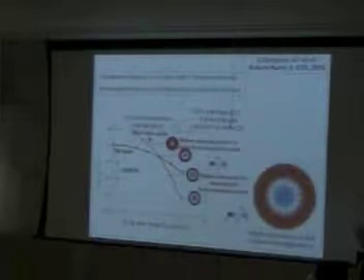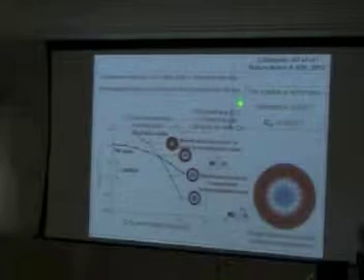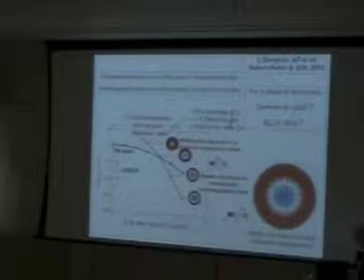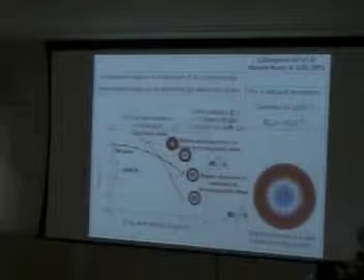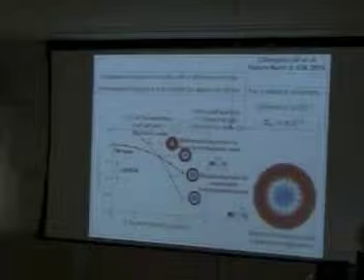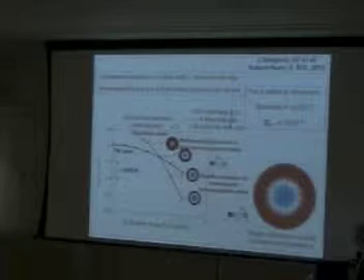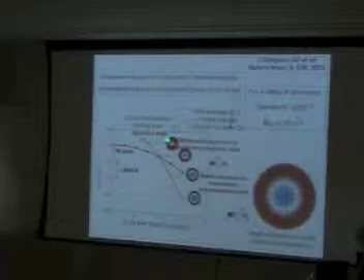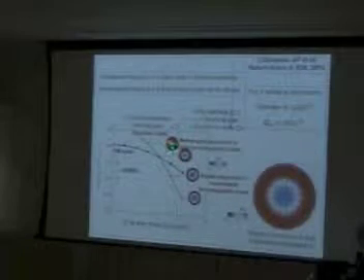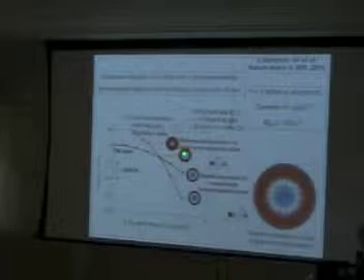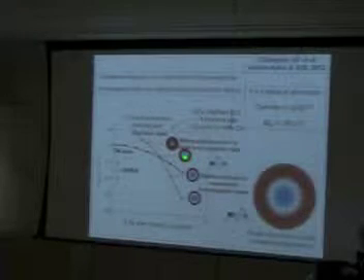What you can see also is what controls the size. In fact, there is a difference compared to the skyrmion lattice. When you have a skyrmion lattice and we increase the Dzyaloshinskii-Moriya interaction, the system tends to create more skyrmions of smaller size. But when the confinement is important, when you have created a single skyrmion and the number of skyrmions is fixed, you have not the choice, then the variation of the diameter of the skyrmions is different.